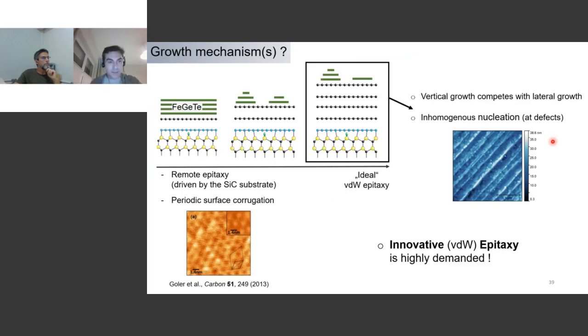In this case, we're still not completely clear, but it's interesting that it seems that we are having 2 effects there. The first contribution could be coming from the substrate. What I mean by that is that the silicon carbide might be influencing growth through an effect that is called remote epitaxy. So silicon carbide is actually driving the epitaxial alignment of FGT, and it's also allowing for a much higher adsorption rate of atoms at the surface. So it's a much more reactive surface. That's why you are able to grow a thicker FGT.